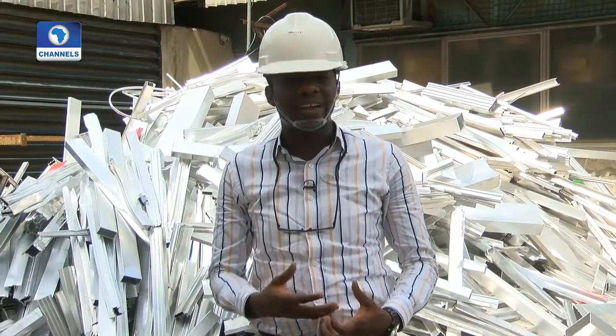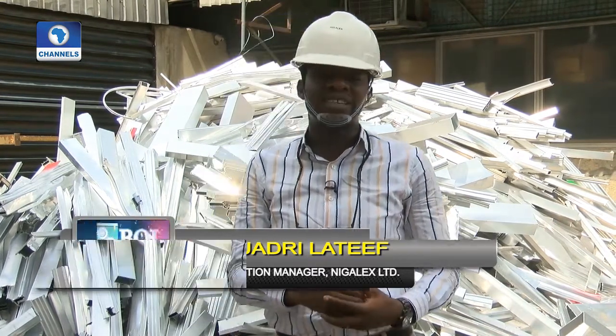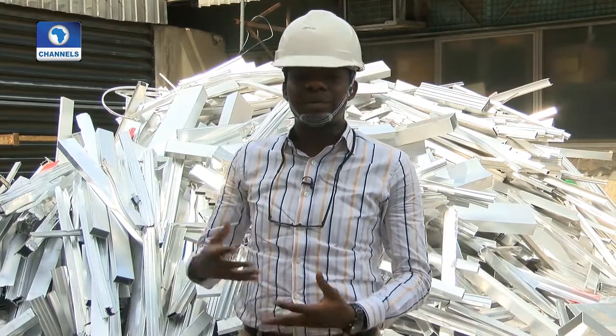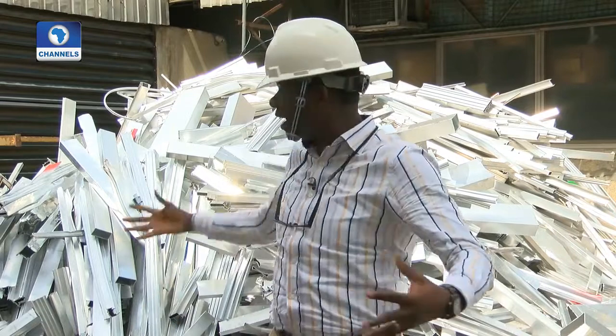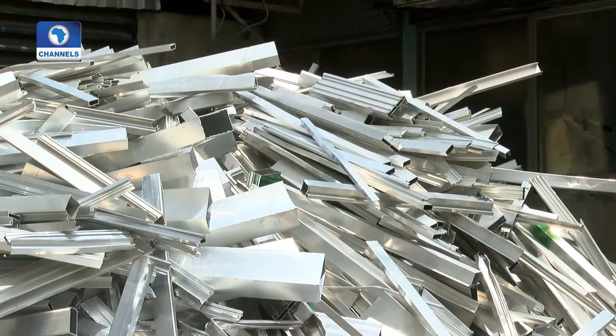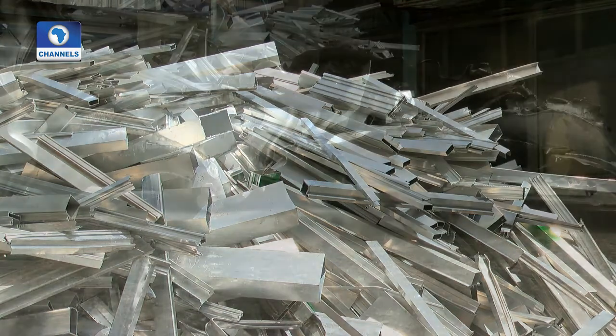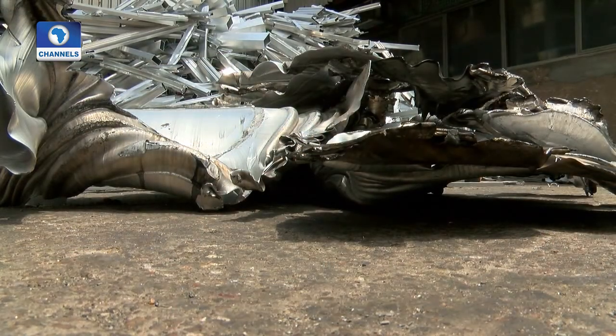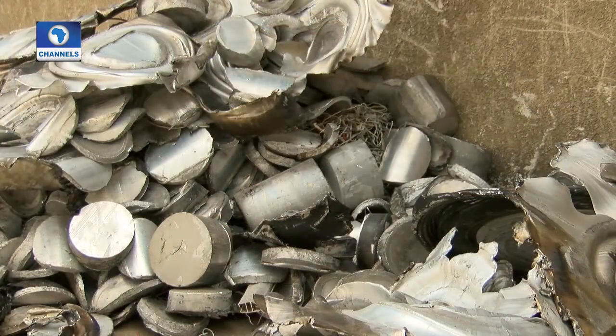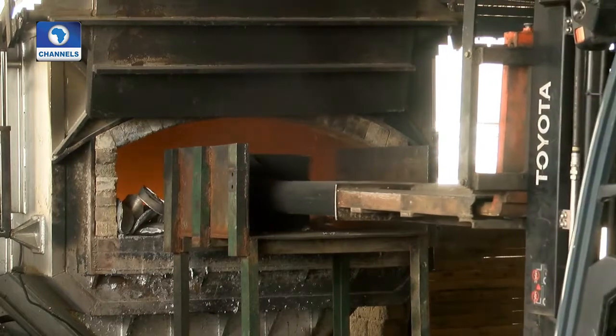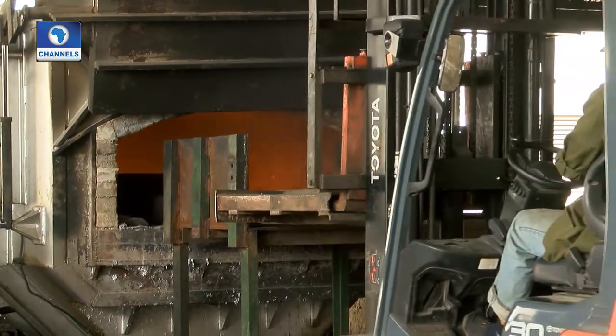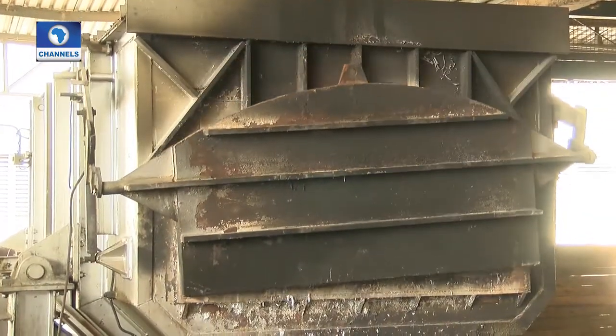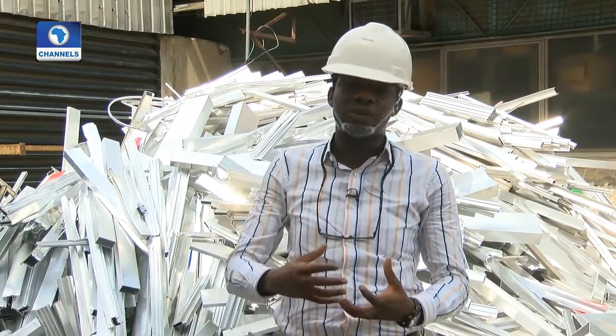We also manufacture this raw material here, basically, because we use about 40% to 50% of our internally generated scrap to get our raw material, while the remaining is imported from abroad. As you can see behind me, these are the scraps that are generated from the extrusion line, meaning in aluminium there is nothing like scrap. Even when they are generated at the point of extrusion as scrap, we still make use of them as input into production at the point of remelt, meaning that we heat them in the oven at the remelt to a particular degree, after which we use the table there to cast the log. Although, when we compare this log to the imported one, there is only a slight difference in terms of the flow at the point of extrusion.